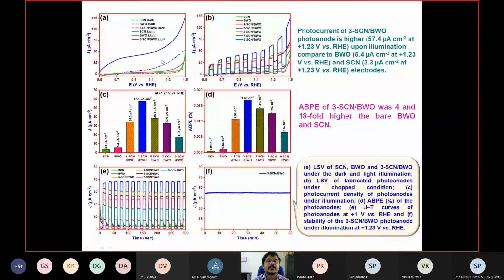Later, we did the photoelectrochemical studies of this material. Especially, you can see this. We have chosen sulfur-doped graphitic carbon nitride, bismuth tungstate, and then the heterojunction. The dotted line shows the linear sweep voltammogram obtained in the dark condition. The solid line shows the material exposed to light. At that time the linear sweep voltammogram is enhanced. Likewise, while recording the linear sweep voltammogram, we chopped the illumination. You can see we varied the different weight percentages of graphitic carbon nitride and recorded the photocurrent for hydrogen production. Among these three, sulfur-doped graphitic carbon nitride with bismuth tungstate showed 57.4 microampere current density.